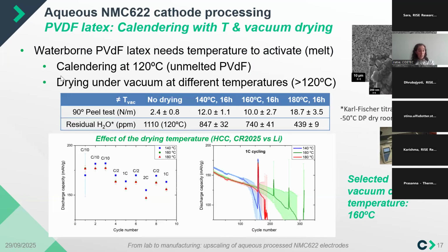On the drying step, we also look at which temperature to post-dry, to find the threshold and reach at least below 500 ppm of residual water, measured by Karl Fischer, in order to confidently proceed to assembling well-performing cells with these waterborne electrodes.